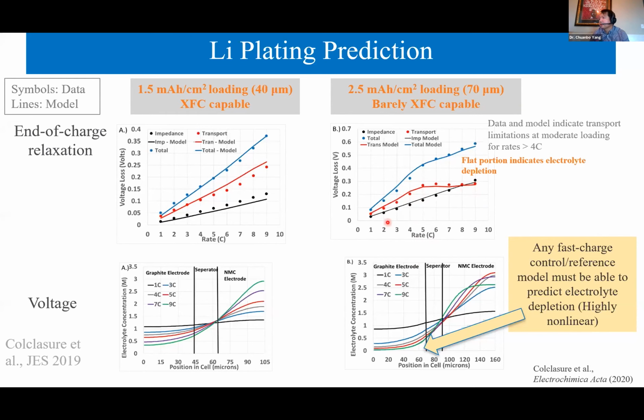But this works perfectly for a single layer cell. We tried to apply this technology to cylindrical, commercially available cells, and found that it was affected by the temperature a lot. So we need to do a lot of calibration before we use this method to determine whether electrolyte behavior, at least, is a limiting factor or not.